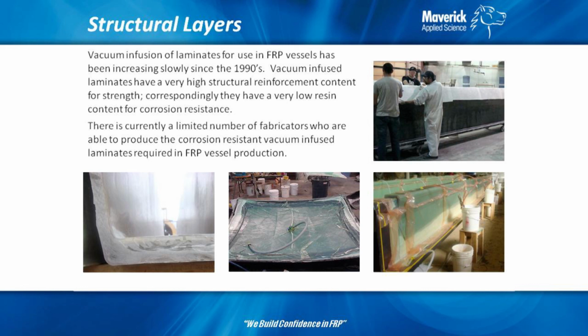Vacuum infusion is still fairly rare. There are some companies that do very well with vacuum infusion, but they are few and far between. Vacuum infusion provides a really high strength part. It is typically much higher in glass content, so these parts can be less corrosion resistant. If you need a corrosion resistant part that's vacuum infused, typically there will be a secondary corrosion barrier added, or the corrosion barrier will be put down first and act as the initial boundary for all the other glass fabric to be vacuumed to. Still not very common. You will only see it in your highest end manufacturers.